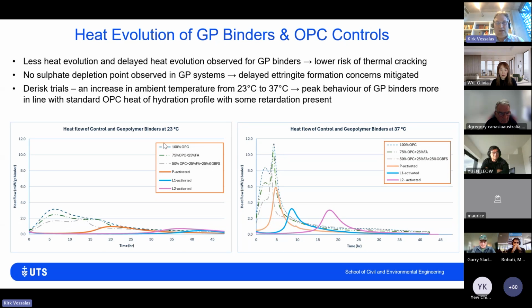And what you see, whether you cure at ambient conditions of 23 degrees Celsius or at a little bit higher temperature, is that there's less heat evolved in the system as we move forward with time. There's also a little bit of retardation, but the most important thing here is that we don't really see any sulfate balance or depletion points that occur within the geopolymer systems.